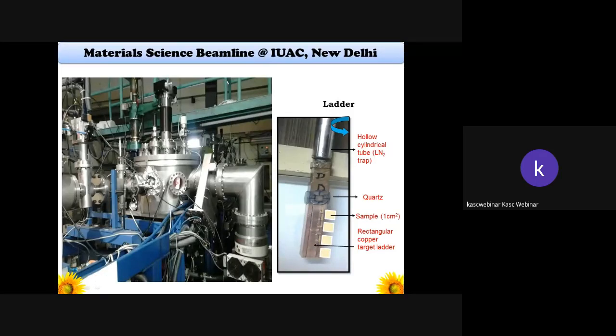Here we can see the materials science beamline available at the Inter-University Accelerator Centre, New Delhi. In a ladder, we can place the samples; the right side of the figure clearly indicates how the ladder looks. In a hollow cylinder, we can fill liquid nitrogen. By using a quartz, we can identify where the ion beam irradiation path goes inside the material. We can fix 4 samples on a single face of the ladder, so we can have 4 faces at a time. We can irradiate 16 samples one by one, and the sample dimensions are restricted to 1 by 1 centimeter.